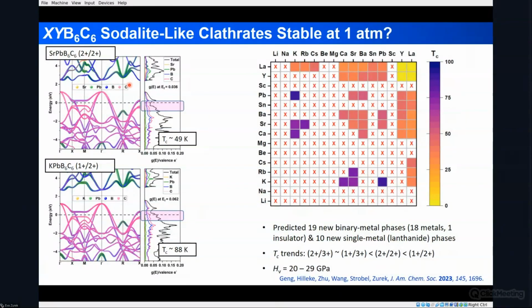If, on the other hand, you have a different valence, so 2+ or 1+ or some kind of combination of them, you are going to be varying the position of the Fermi level. And if you can engineer your system so that you hit one of these high peaks in the density of states, then you could potentially get a very high TC. And one can do that. If you take a look at the trends in the TC, we see various trends. Systems that hit this peak, that have an average valence of 1.5+, have the highest TC, with this potassium lead compound, this is at 1 atmosphere, having the highest TC of 88 Kelvin.